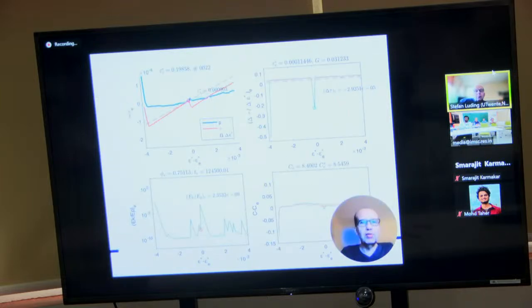This is now the zoom into one event. We are looking at stress, we are looking at modulus, we are looking at kinetic energy, and we are looking at coordination number. At the top left, you see the shear stress. That's the orange line, and there's the stress drop, shear stress drop. The blue line is the hydrostatic stress. Actually, there's a little bit going on, but not much. Only a wiggle, no drop. Okay, so hydrostatic stress and shear stress are qualitatively behaving differently for this event.